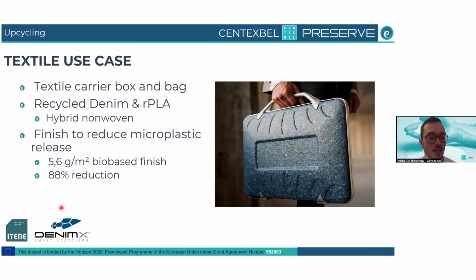And then after this, this non-woven will also be finished with a microplastic reducing coating to reduce the microplastic release, and then create this kind of carrier box. So this is after thermoforming as well, with recycled PLA material.